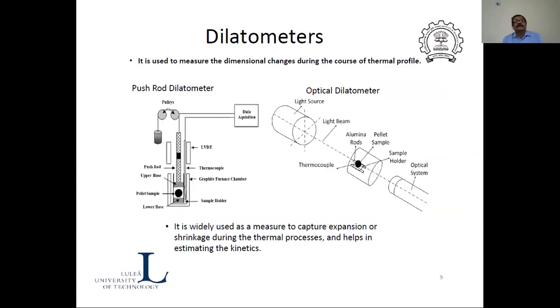So what we did was, we know that sintering leads to a shrinkage. So we actually did a very simple experiment. It is called the heating microscope, which I think many of you may be aware of. For example, if you want to find out the ash fusion point, you take a small pillar and put it inside that heating microscope. There is a light source, and then you get a shadow image. That way you'll be able to capture how the size is changing. From there you can find out when it is going to soften, etc. So the same system we took.